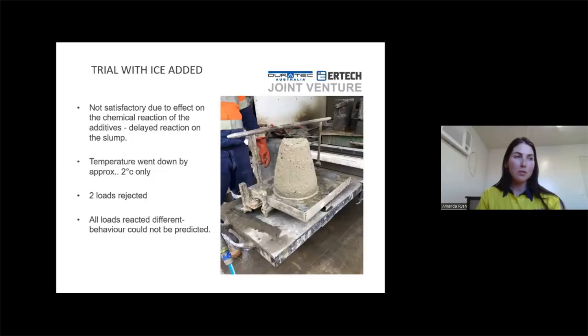So the trial with ice was, unfortunately, not satisfactory, due to the chemical reaction of the additives. Our mix design was a specific mix, not your standard average. It is a very specified mix with a lot of additives in it, and it also had a material known as Xypex in it. The reaction with the additives and ice just wasn't happy. It didn't work, and unfortunately we got a delayed reaction on the slump.